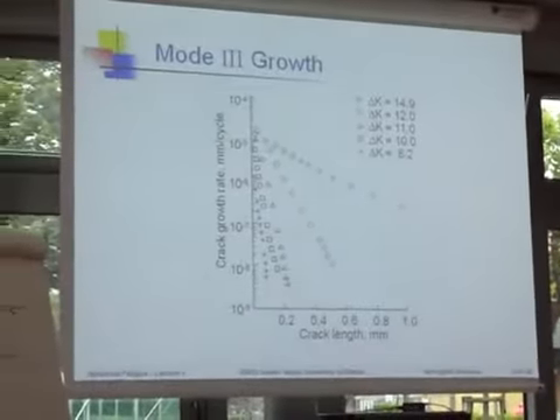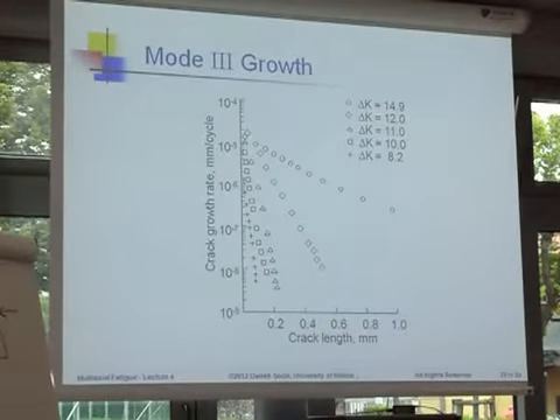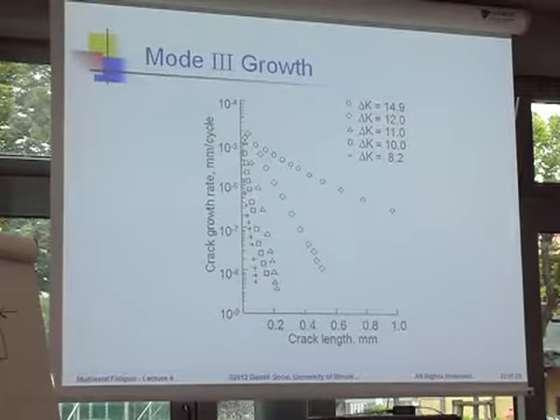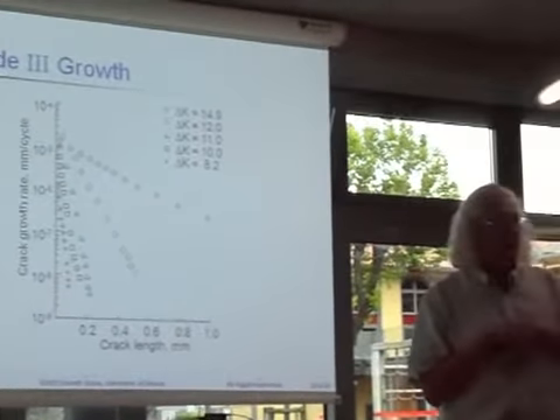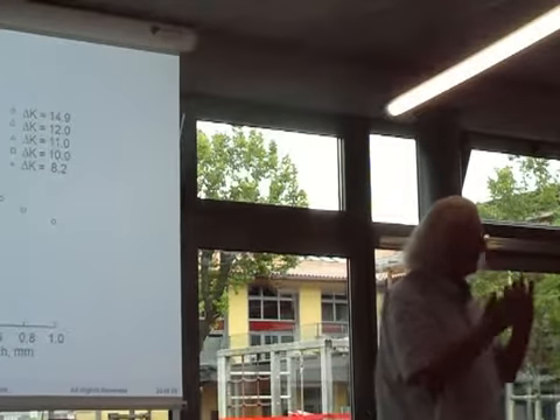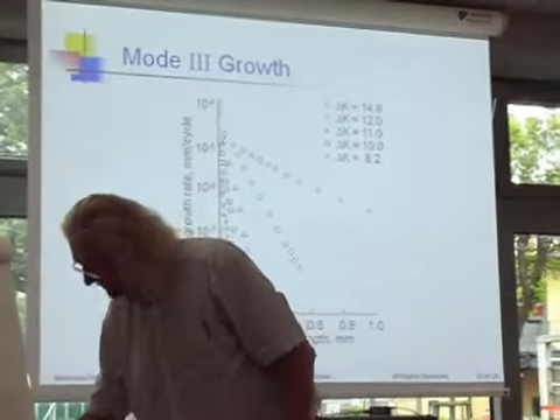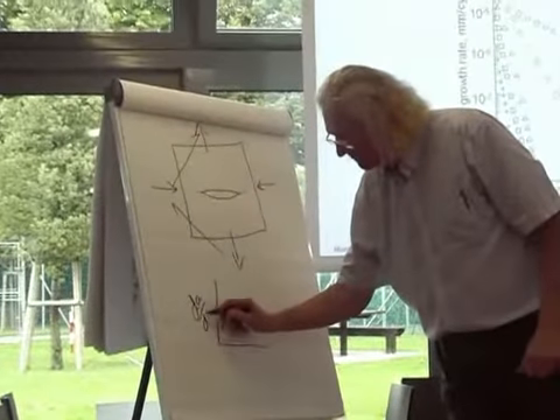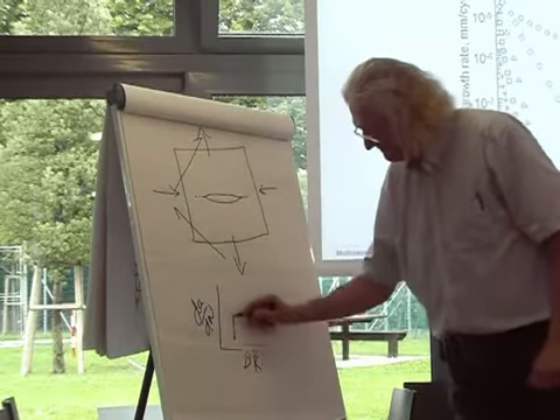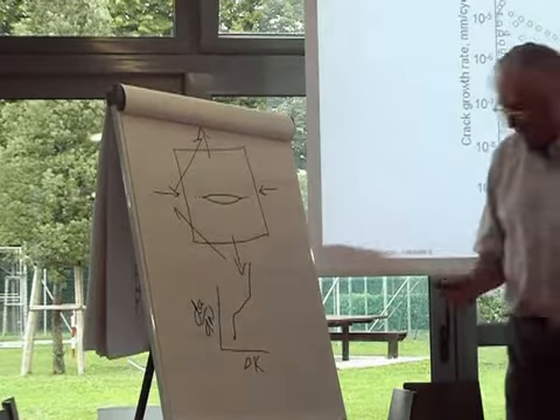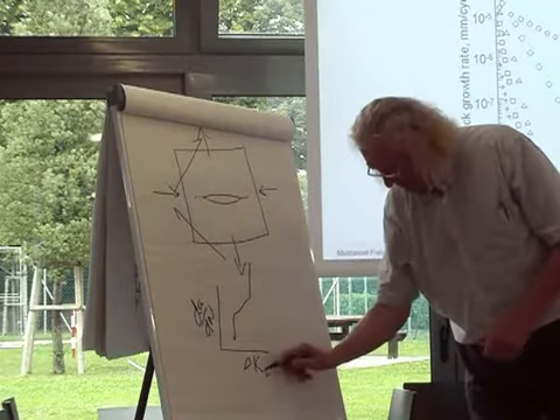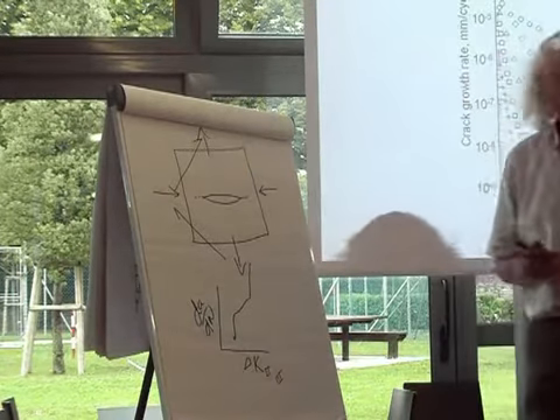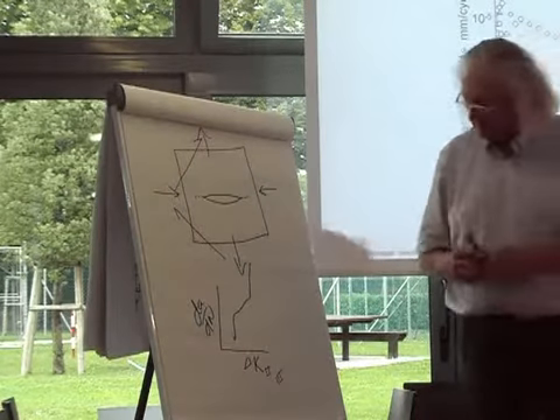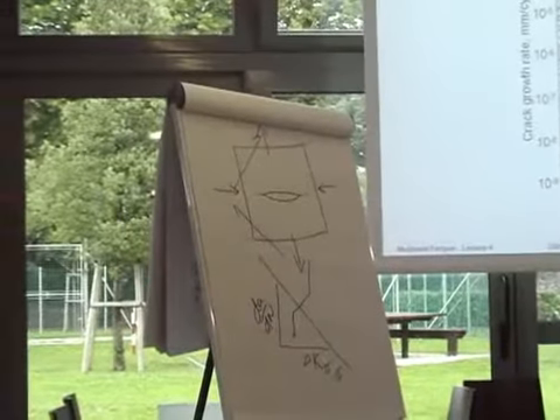And here's what happens if you forget about that. We have this idea that we can go find some data in the literature. So here is some very nice data for mode 3 crack growth. Very carefully taking data and so on. And we have this idea that there's a unique relationship. We say, fine, I know the growth rate looks something like that. So there's a one-to-one correspondence between stress intensity, and we can let this be mode 2, or we can let this be mode 3 if we like, and so on. And not at all true. Let's just look at this data.